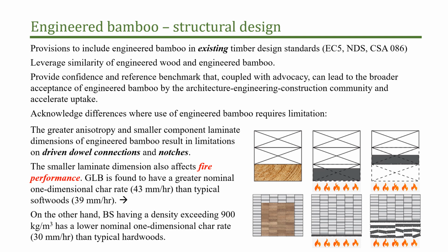One of the biggest differences between engineered timber and engineered bamboo is actually in terms of its fire performance. Because of the small laminate size, we end up with an effectively greater char rate than we would see in typical softwood engineered lumber. And that really is a function of simply the small laminate size. As the fire reaches the first glue line, that outer laminate is assumed to spall off, exposing the laminate beneath it and so forth. If you think about that with a very thin laminate, you end up with a more rapid degradation of the material, and that needs to be addressed, and it certainly can be addressed, and we have some proposals out there for addressing this issue. There are still some questions associated with that.